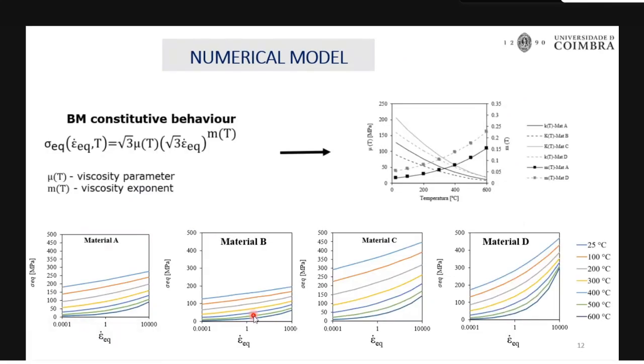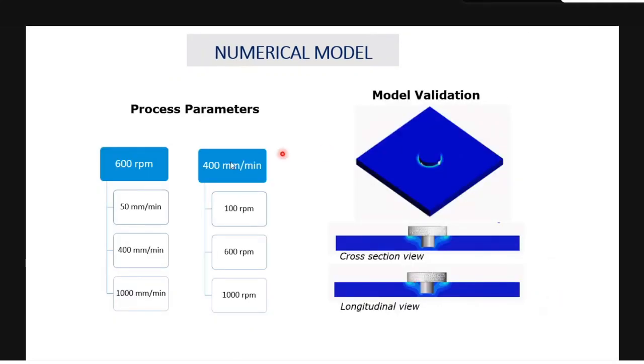Coming to here, you can see the equivalent stress for different strain rates plotted. Here you can see how the material behaved. By changing this viscosity parameter and the viscosity exponent, the flow strength of each material is different. So this parameter is included, and these are the different process parameters used for the simulation. With 600 RPM as constant, I varied the tool travel speed, and 400 mm per minute is the travel speed set as constant while the other was changed.